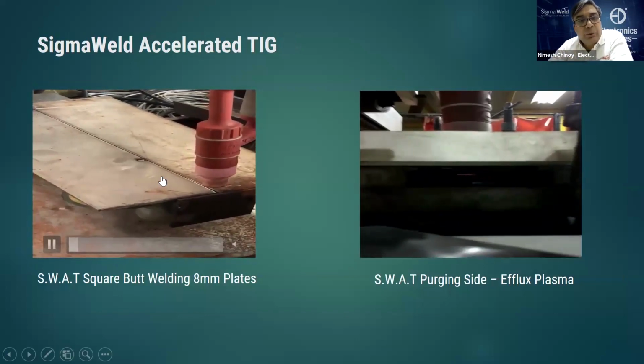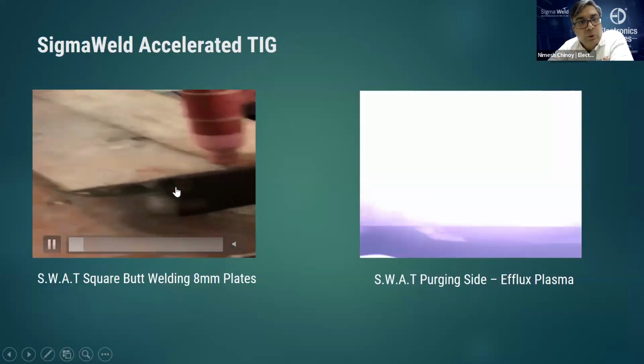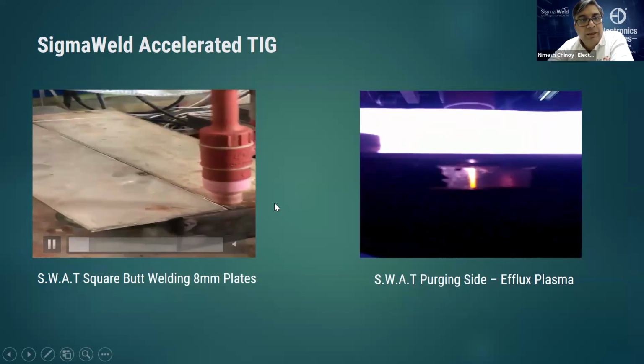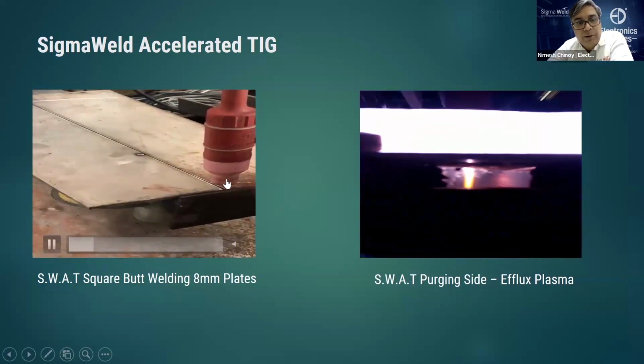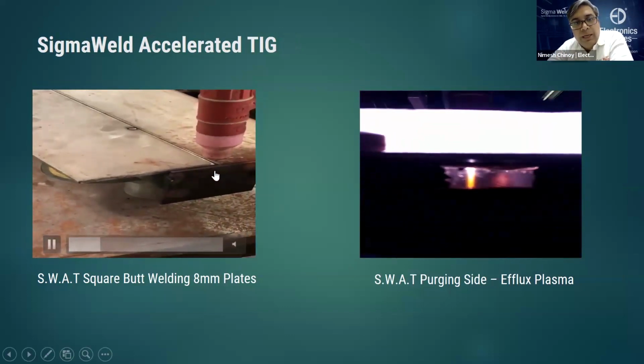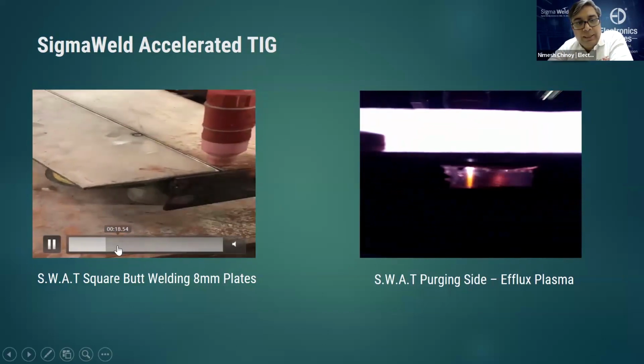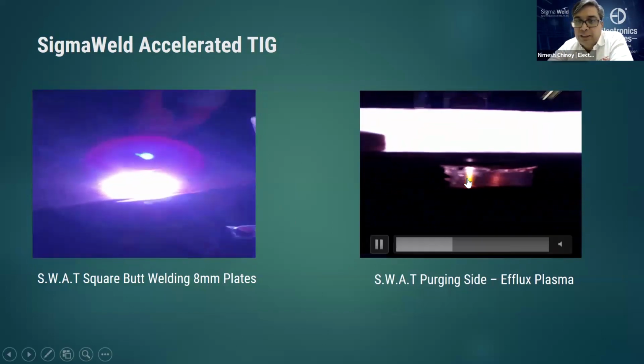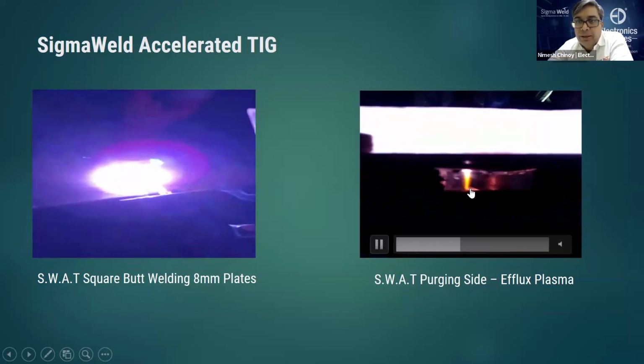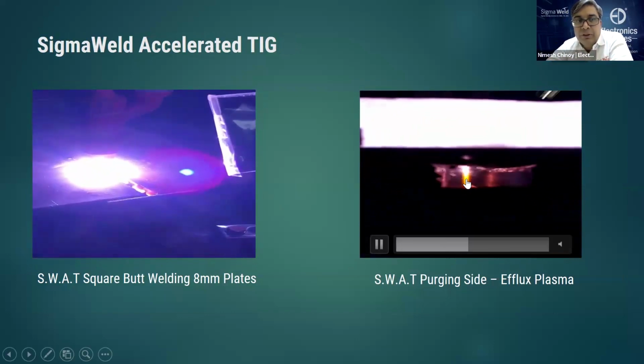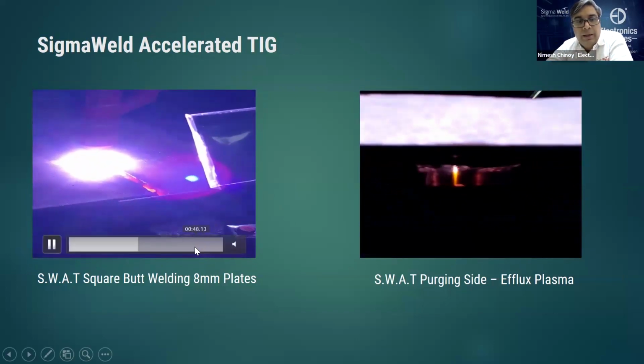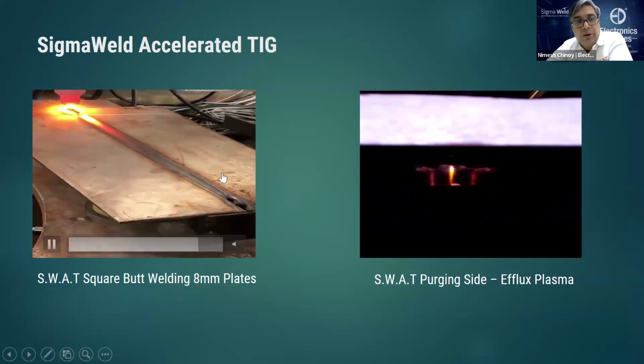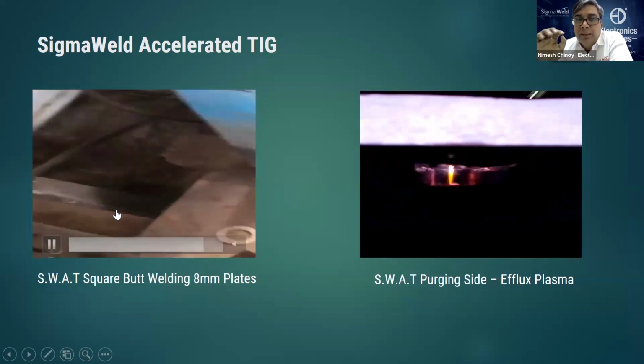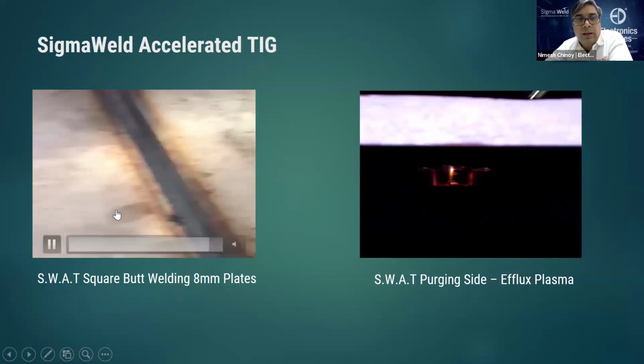So this is how it looks. Basically, you can see a square edge preparation. There is no V shape done. It's a regular TIG torch, but it's going to be mounted onto the SWAT mode. It will punch it through the entire system in one go. You can see the efflux plasma exiting from the other end, which means there's a clean 100% penetration joint. And the welding speeds are upward of 400 millimeters a minute. So 8 millimeter thick plate can be welded very, very quickly.